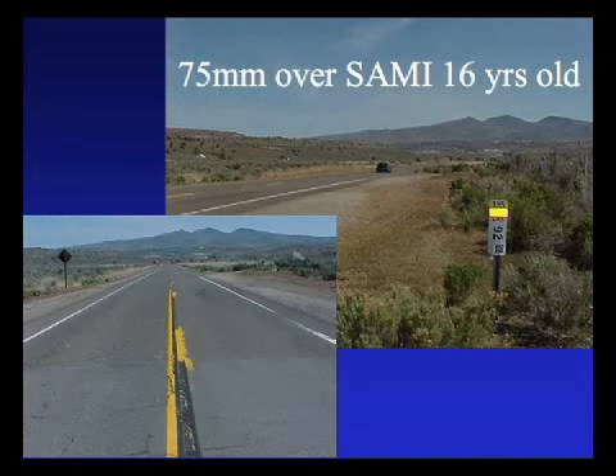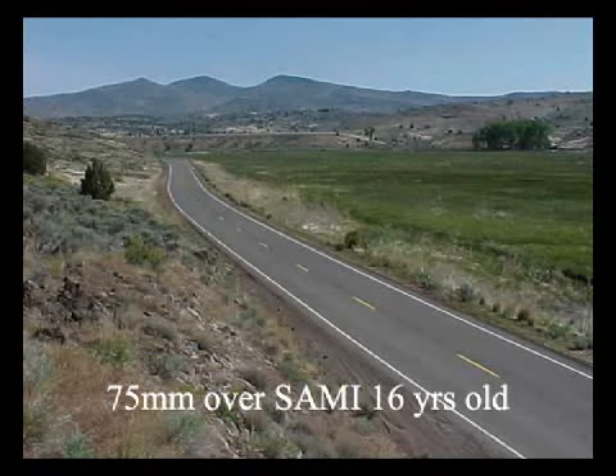In the foreground is the rehab they did, and this rehab is I think around 6 or 7 years old at this point. I'm talking about the rehab, whereas this was 16 years old. These sections on both ends, the last two sections that were there, the pavement was getting so bad they had to rehab it, so they overlaid those sections. But you can see that after 16 years, that's why we got very excited about reduced thickness asphalt rubber mixes.